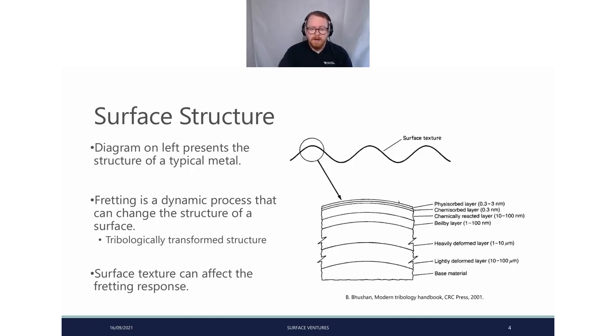Okay, so surface structure. First of all, let's review the standard structure of a surface. We have our surface texture or roughness, and we have multiple layers: physisorbed and chemisorbed layers, a chemically reacted layer up to 10 to 100 nanometers, then our amorphous Beilby layer, and then the various deformed layers depending on the mechanical loading of this material. Fretting is a dynamic process, and this can change the structure of the material, specifically the tribologically transformed structure, which has been covered in literature quite extensively, and I will be talking a bit about this later.